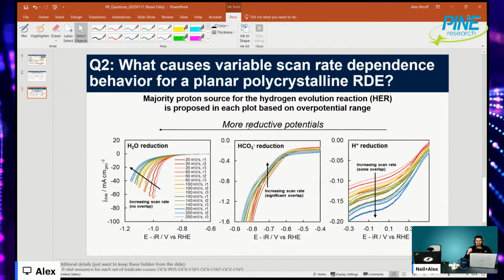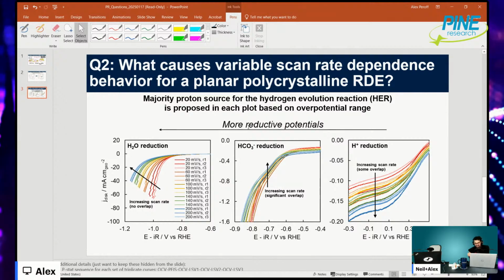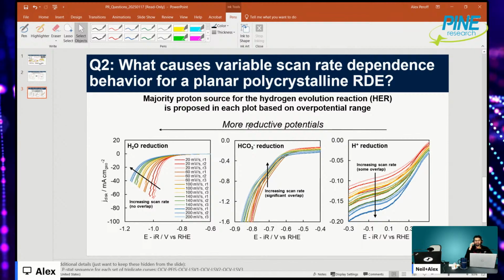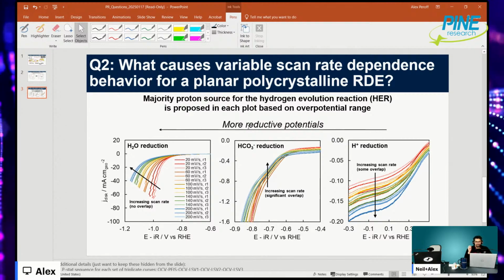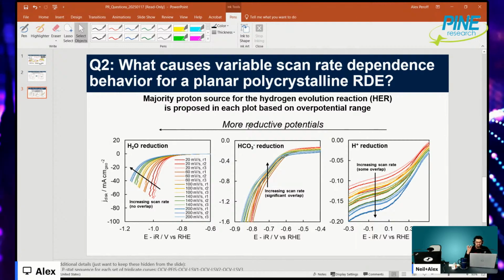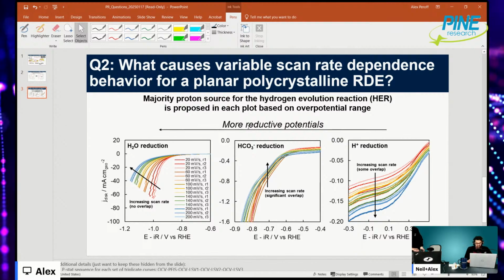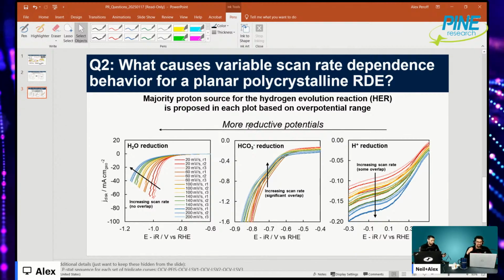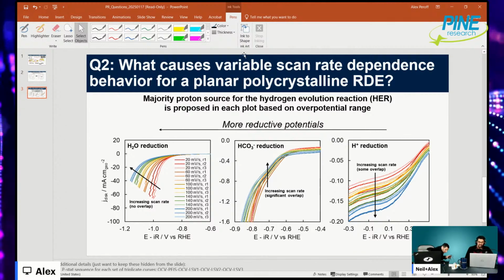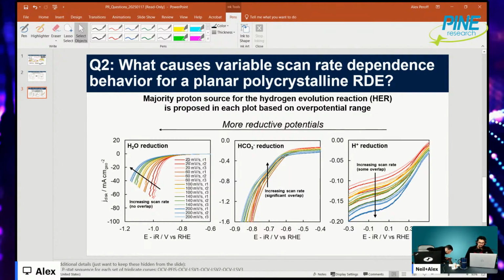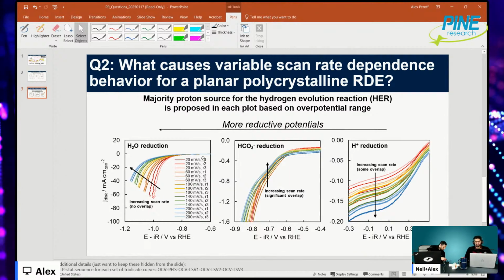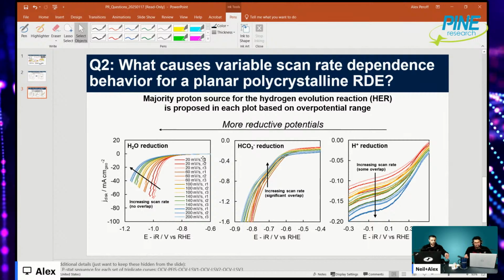Now, I mentioned in the previous live stream that you ideally want to do RDE at as slow a scan rate as possible. RDE is not designed for these fast scan rates like 100 and 200 millivolts per second. Even 20 millivolts per second is actually fast. RDE is supposed to be a steady state reaction.